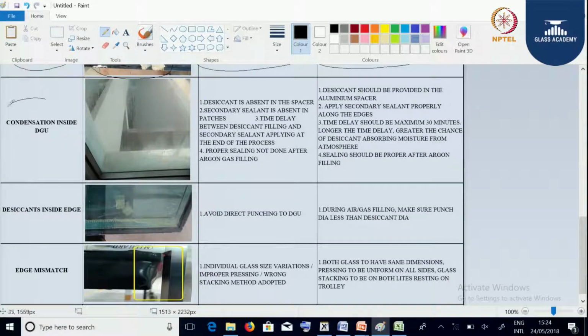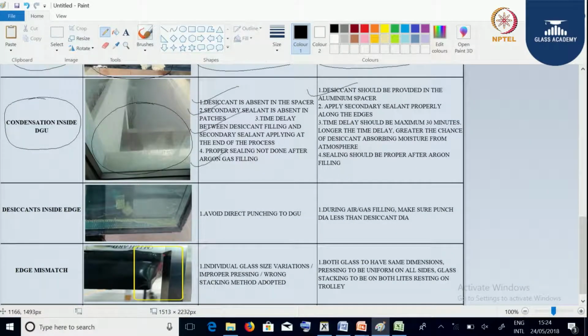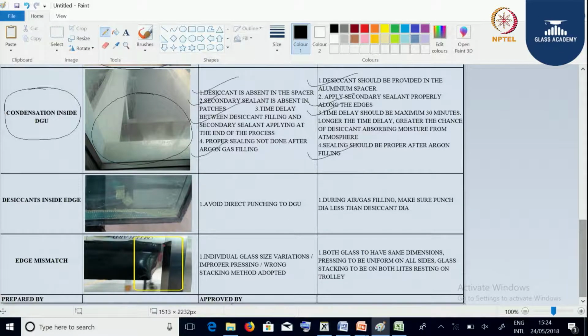Next defect we are going to get is condensation inside the DGU, where moisture is trapped inside. The reasons being desiccant absent in the spacer, secondary sealant absent in patches, a time delay between desiccant filling and secondary sealant application, or improper sealing after argon gas is filled. We can overcome these issues by ensuring desiccant is provided in the aluminum spacer, applying secondary sealing properly along the edges, keeping the time delay to a maximum of 30 minutes (since a longer delay increases the chances of desiccant absorbing moisture from the atmosphere), and ensuring proper sealing after argon gas is filled.